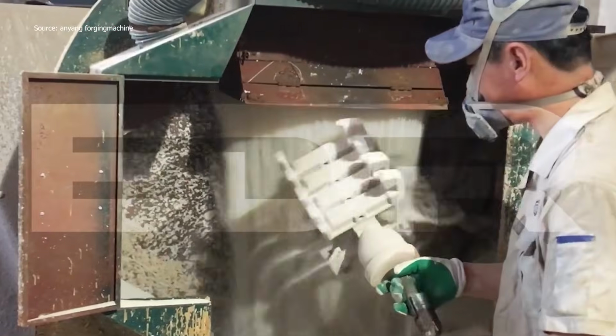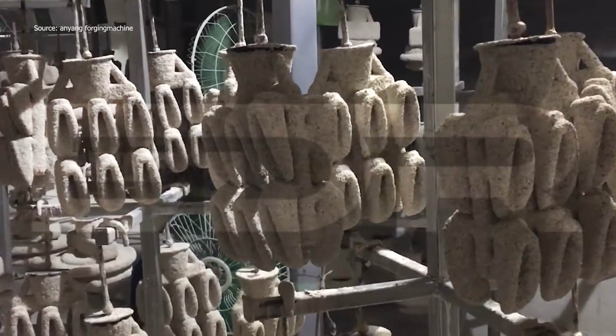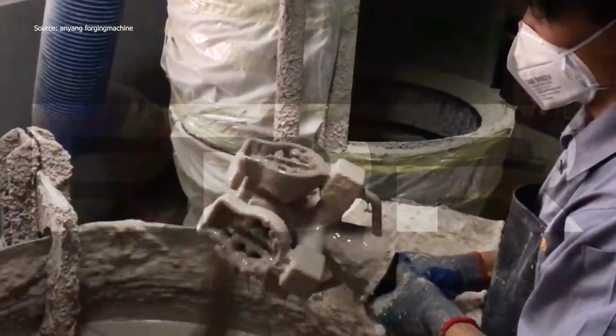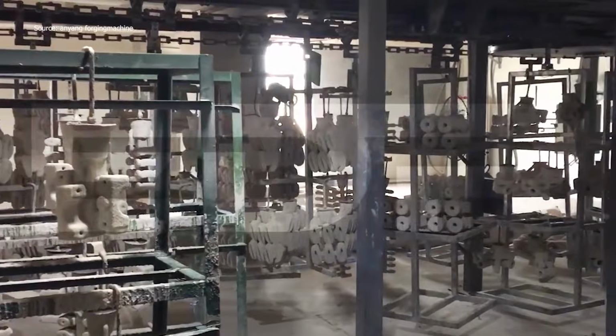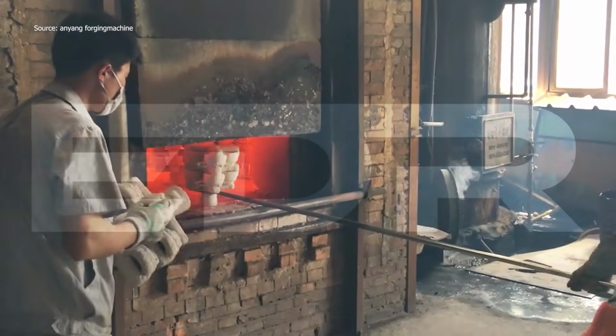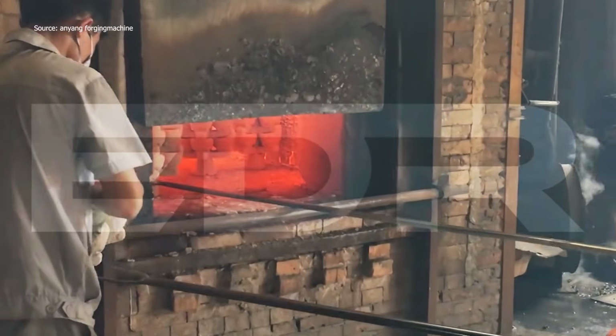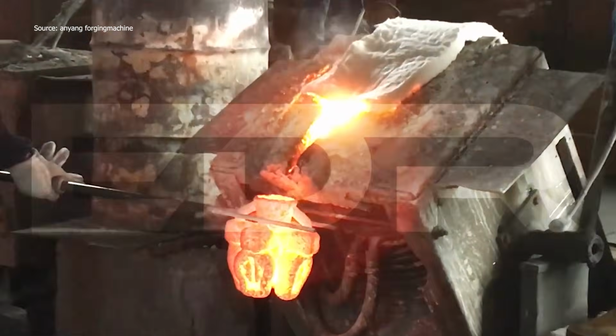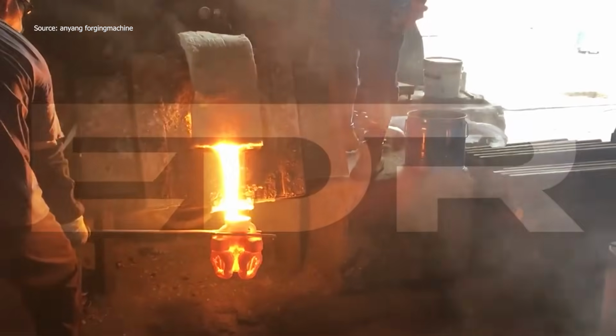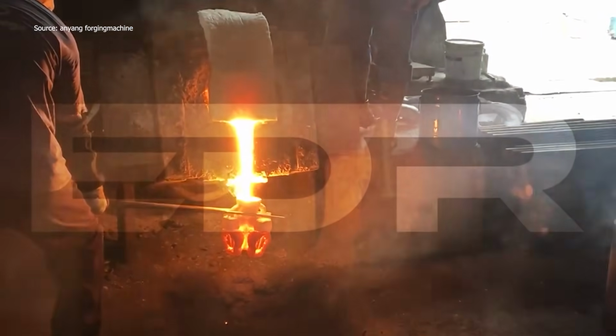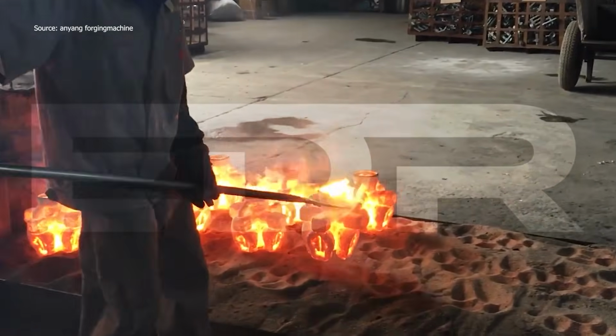Shells are then fired at over 800 degrees Celsius before molten steel is poured in. Every cavity fills with precision. After cooling, the ceramic is broken off using vibration. Circular saws remove each casting from the cluster. Depending on the application, parts are then heat-treated, machined, or chemically finished. There's something captivating about watching temporary wax become complex metal. This lost wax casting process combines ancient technique with modern precision.